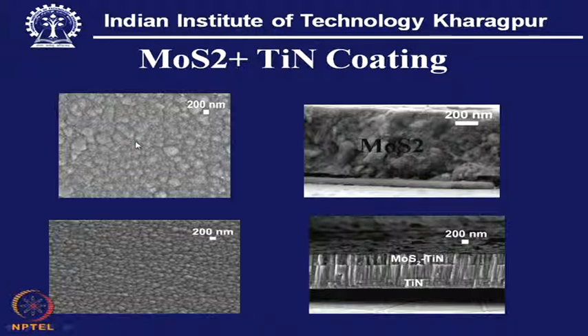This type of structure or morphology has a limited application under vacuum environment, with all those satellite mechanisms, and in those cases this is a good coating. But our purpose is to improve its performance, so that MoS2 can be used in one of the most important tools, that is the cutting tool. We know that titanium nitride is already well known as a hard coating. So, on one side we have a soft coating and on the other side a hard coating, but when we put them in right proportion, what is the outcome? That outcome is immediately conveyed by the SEM picture.